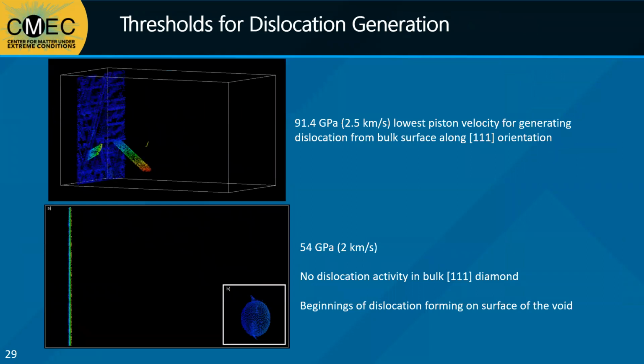In addition to the simulations for 111 diamond at 3.5 kilometers per second, we also performed simulations at varying piston velocity to see if we could find the threshold for defect generation. As low as 2.5 kilometers per second, or about 91 gigapascals of pressure, and without a void, bands of defects would successfully emanate from the impact surface. When the velocity was lowered to 2 kilometers per second and about 54 gigapascals of pressure, we no longer saw these bands form. But when a void was introduced, we did see the beginnings of dislocations starting to emanate from that void.